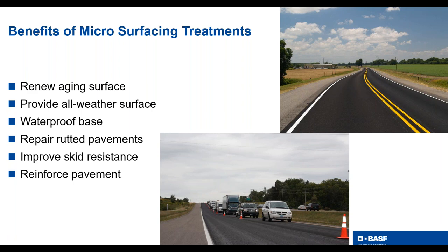Microsurfacing, unlike chip seal, can repair rutted pavements. With the incorporation of the superpave binder specifications, there have been fewer and fewer rutted pavements, but honestly, that's what microsurfacing was first developed to do. As I mentioned, it also improves skid resistance greatly and helps reinforce the pavement overall, especially if you're doing some rut filling, because some of those ruts can be pretty deep that I've seen filled with microsurfacing. So we'll get into a couple more pictures here.